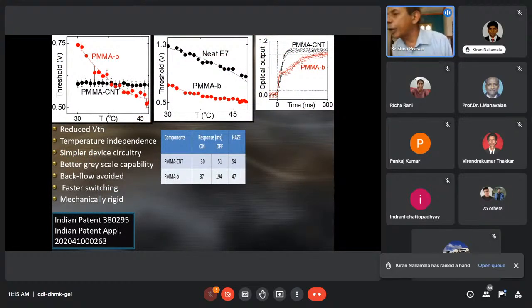One main aspect of these kinds of systems wherein you are reinforcing the polymer network is the threshold voltage, the voltage which is the operating voltage for any liquid crystal device. At such a voltage, there is a reorientation that takes place from one orientation to another. It is what gives you the bright and the dark states in a liquid crystal device. And that threshold voltage is a strong function of temperature because of the associated elastic constants involved. It goes like the order parameter squared, so you have a strong dependence for such a threshold. But when you reinforce these polymers, the kind of surfaces you create overcome all these influences from the elastic constant of the medium and keep the threshold voltage more or less constant with respect to temperature, which is an important parameter because for a display device to work, you need to be attentive to the threshold voltage that is needed to drive the system from one state to another.